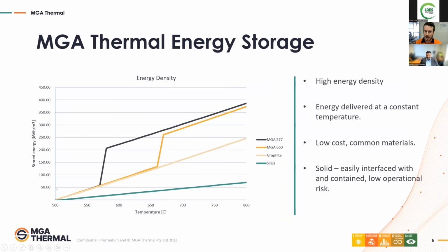So for the thermodynamicists amongst us, an enthalpy plot, just looking at the stored energy density, so kilowatt hours per cubic meter as a function of temperature, baselined against a couple of other media that are used to store thermal energy. You can see that we have the gradual increase in stored energy with temperature, which is sensible heat. And then we have these kick-ups, which are the latent heat occurring at a couple of different temperatures for different materials that we've developed. And really, there's a lot of science that goes into that for us.